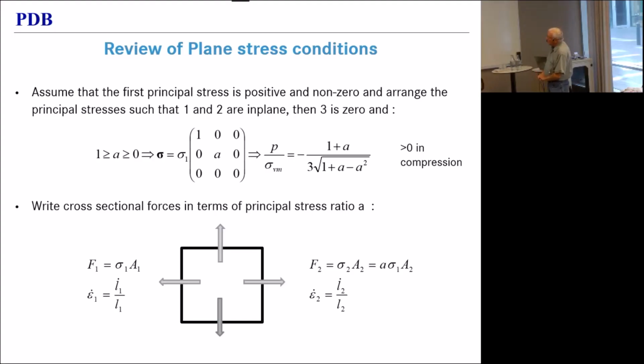First, you have to prepare some notations. He was looking at plane stress conditions. And in fact, he was looking at biaxial tension. So two principal stresses that are both in plane and both positive. And then you can write a stress tensor as the first principal stress multiplied by a matrix where we have a 1 in the 1,1 component, a value A in the 2,2 component, and 0 for all the others. That factor A is the ratio of the second principal stress to the first. And if you work it out, you can calculate the triaxiality, which is pressure over von Mises stress, and you see that that is a function of A. So this A contains the same information as the stress triaxiality. You can identify it with a state of stress.